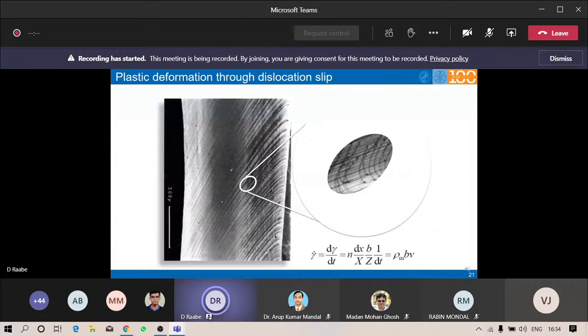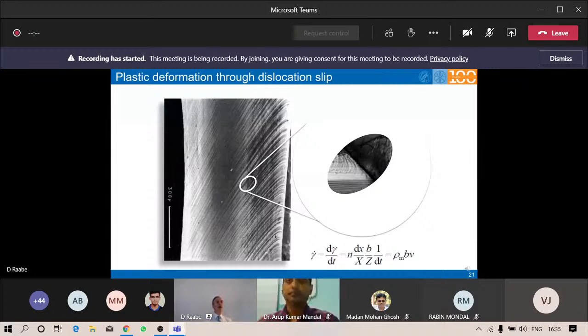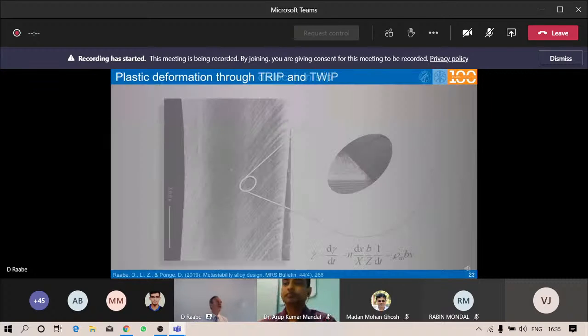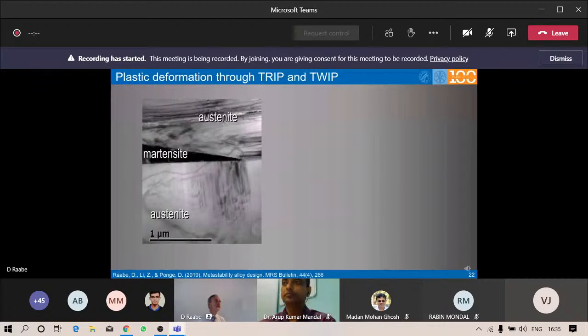When you want to describe the strain hardening, you have, like in a Kocks-Mecking model, to account for the dislocation interaction, or you can consider here the mean free path reduction, like shown in this little animation or movie. When a grain boundary is in your way, then you can describe the reduction of the mean free dislocation path in a harmonic way, where you add up in a harmonic formulation all the obstacles that are in the path of a moving dislocation set, and that would contribute then to the strain hardening in the case of a Taylor formulation. What is really important for more complex steels are TRIP and TWIP effects.